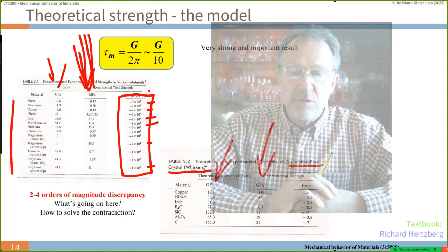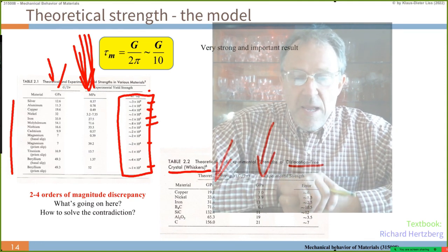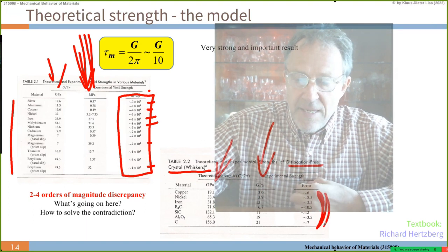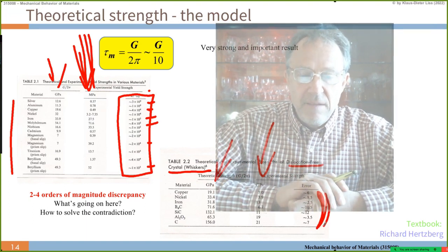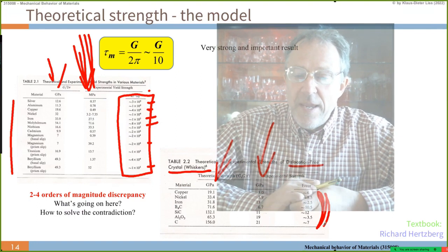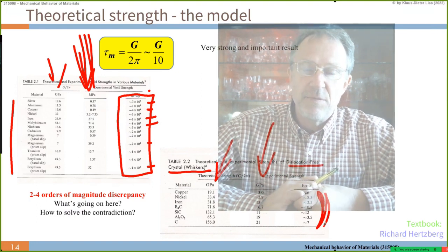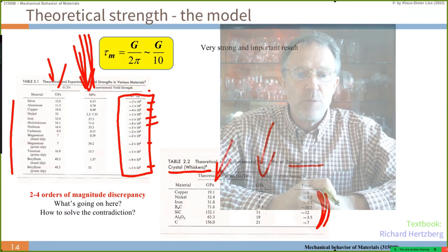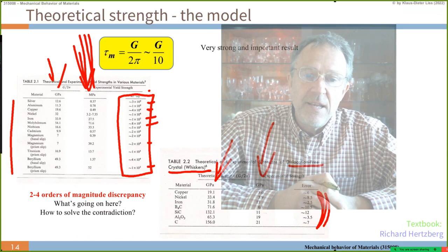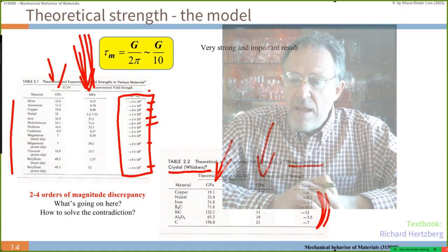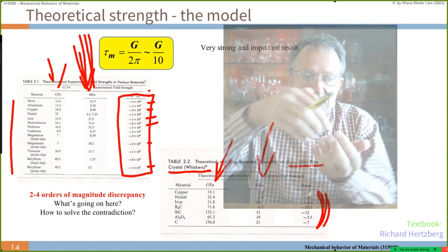This is something we want to note down already for later. But still, it is a factor of about 6 to 10 on average weaker than the theoretical yield strengths we have estimated. So still there's the question: what is happening? Why are we not reaching the theoretical yield strengths? Or why does our model, displacing the layers like a stiff cardboard, not match?